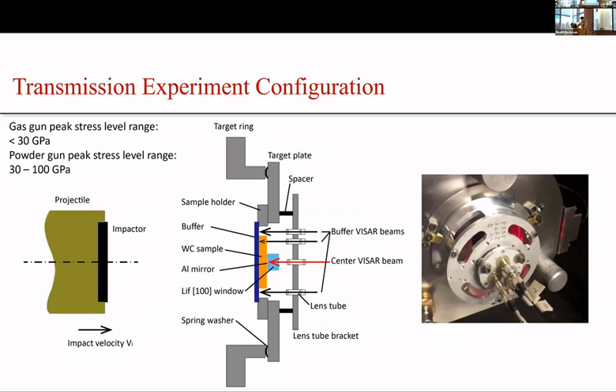This is the diagram for the experimental configuration for the first set of experiments. The impactor is bonded to the projectile, which travels through the gun barrel and hits the target on the right. At the interface of the sample and the window, indicated by the orange block and the light blue block, the particle velocity will be monitored using laser interferometry to get the shock wave loading profile. Depending on the desired peak stress level, we use either a gas gun or a powder gun in our facility.